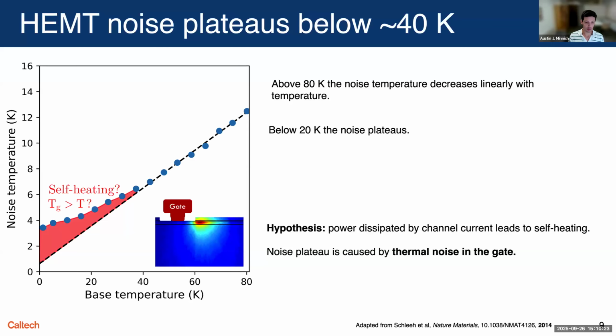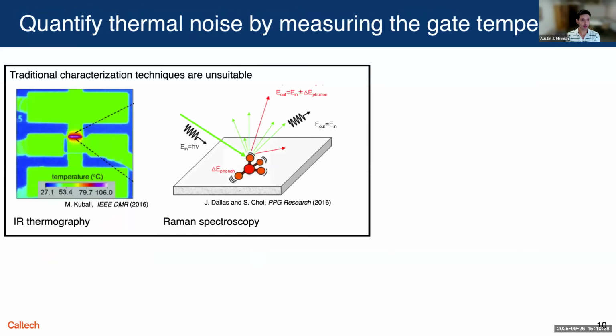So this was work that we did about 10 years ago. And what I'm going to tell you today is how we were able to get more direct evidence that this self-heating is the cause. In the work that you're seeing, we used noise measurements to infer the temperature. What we wanted to do in this study is more directly measure the temperature of the gate. Now, that's not so easy because the gate is half a micron at best for the gate head dimension, and it's buried under tens of nanometers of passivating dielectric. So techniques like IR thermography or Raman spectroscopy are not very straightforward to enable temperature sensing.